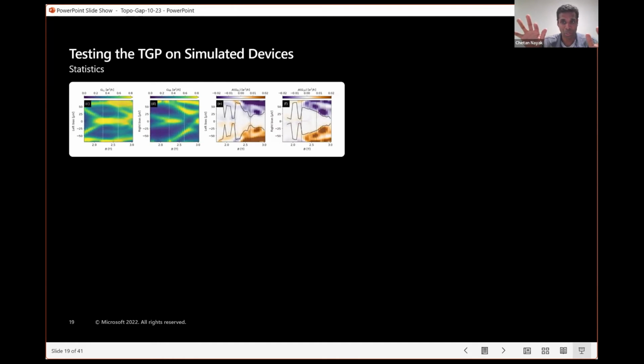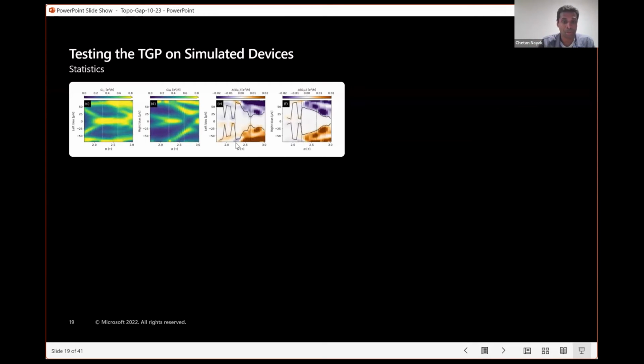So we're both changing the local potential and we're changing the global potential. And you can see there's regions where you have stable zero bias peaks. There are regions where you were asking about the gap closing. Anytime the non-local conductance comes down and the blue and red regions touch each other close to zero, that's where the gap is closed for that value of magnetic field and that value of the plunger gate voltage.